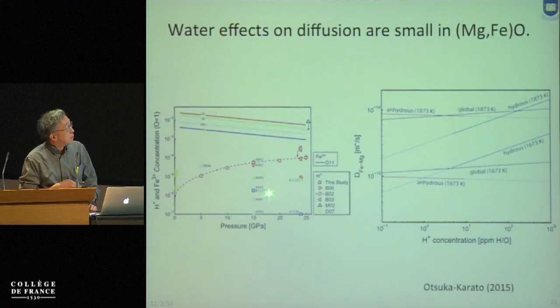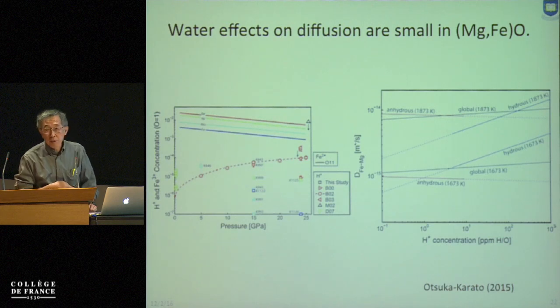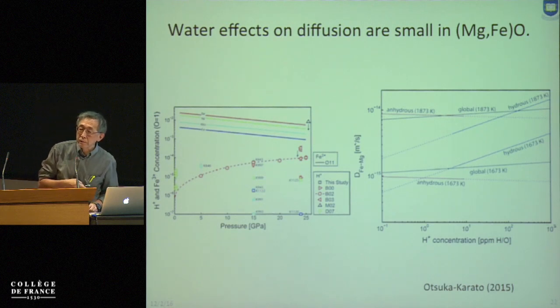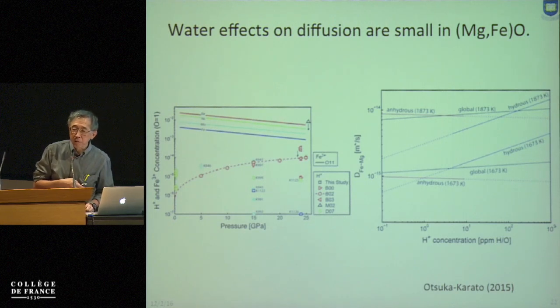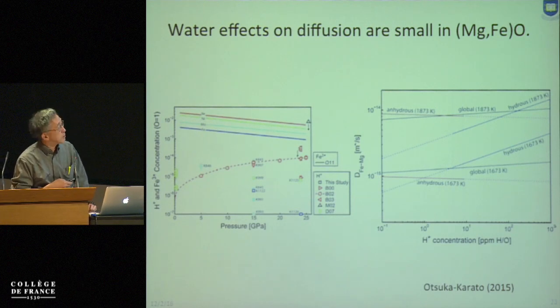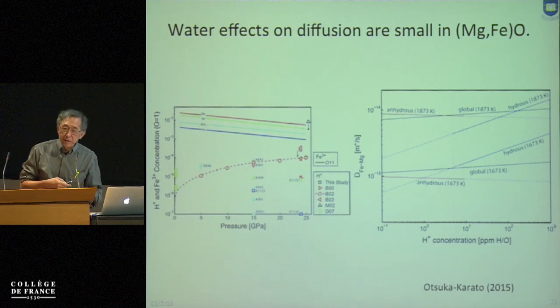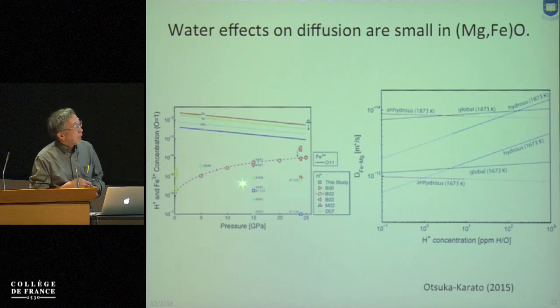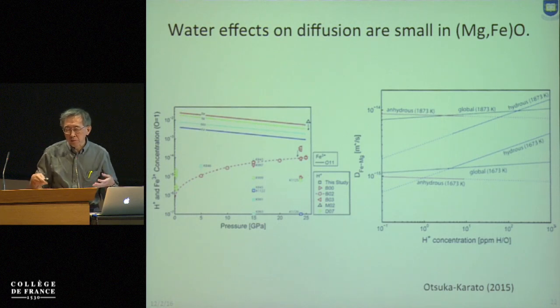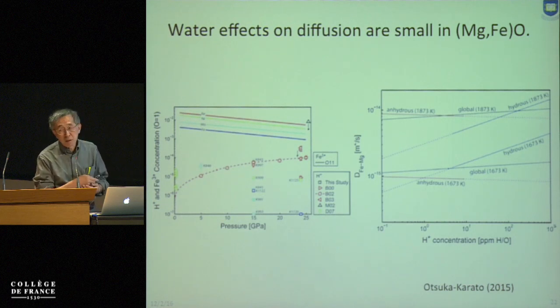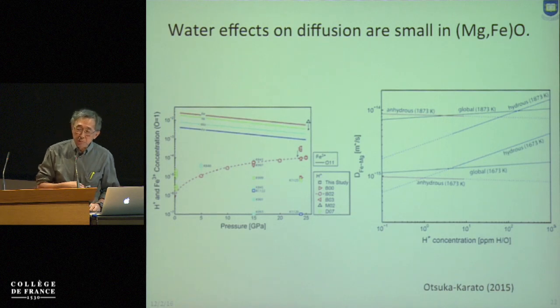So briefly, I want to show you some experimental results to tell you that at least in this mineral, MgFeO, water probably doesn't play any role in the rheology or diffusion. The main reason is, in olivine, if you look at the defects, hydrogen-related defects have much higher populations than the other defects caused by ferric iron. But in MgFeO, ferric iron is much more dominant compared to hydrogen. So therefore, hydrogen plays very little role. So the water weakening may not occur in the lower mantle.